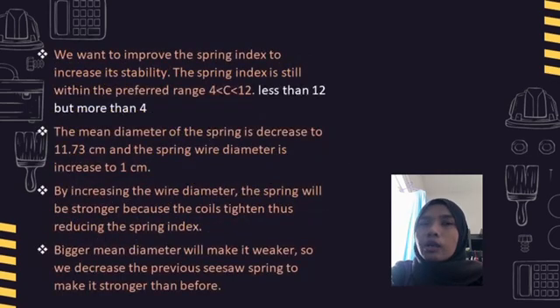We want to improve the spring index to increase its stability. So the spring index is still within the preferred range, which is less than 12 but more than 4. The mean diameter of the spring is decreased to 11.73 centimeter, and the spring wire diameter is increased to 1 centimeter. By increasing the wire diameter, the spring will be stronger because the coil tightens, thus reducing the spring index. The bigger the mean diameter, the weaker it is. So we decrease the previous seesaw spring diameter to make it stronger than before.